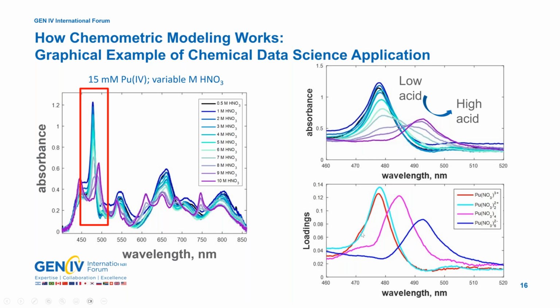And it's exciting that we see that at all, because our lowest concentration of nitric acid in this training set was 0.5 molar. And at that acid concentration, we had probably less than 20% plutonium-4 in the fully aquated state within that system. Despite having only that tiny fraction of plutonium-4 in the aquated position, and absolutely no signal for the fully aquated plutonium-4 at every higher acid strength, our model is still able to pull that out. And that's really powerful.